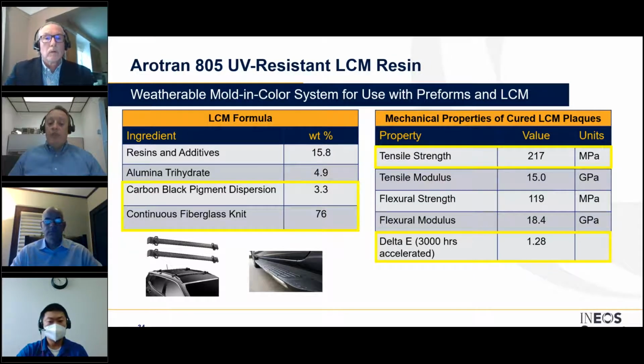The Arotran 805 UV resistant mold and color resin that Dan showed earlier in an SMC application was incorporated here in this LCM application, and we were able to achieve high performance and tensile strength in the direction of the continuous fiber. Although the strength in the tensile mode comes chiefly from the large volume fraction of the knit fiberglass that was used, the appearance and probably also the mechanical integrity of the part after exposure to 3,000 hours of accelerated weathering here by xenon arc technique were preserved by the use of this UV resistant resin formula, where the part that we tested showed a minimal change in appearance with a DE well below 2.